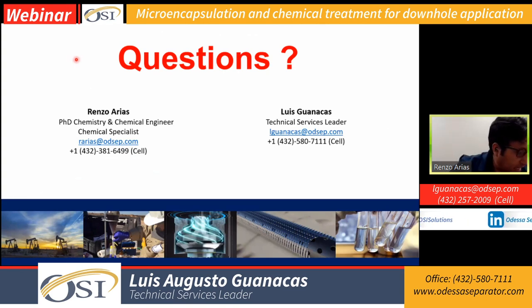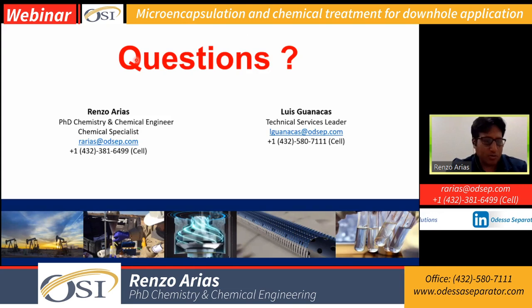Okay, so they're asking me what is the THPS. Like I mentioned before, the THPS is a new alternative for iron sulfide dissolving. THPS actually means tetrakis hydroxymethyl phosphonium sulfate. The main reason these chemicals work for dissolving iron sulfide is the fact that it's a very cationic species. It's very cationic, that means it's going to increase the binding with sulfur. So it's going to act like a scavenger. You may think of it that way. That's why.